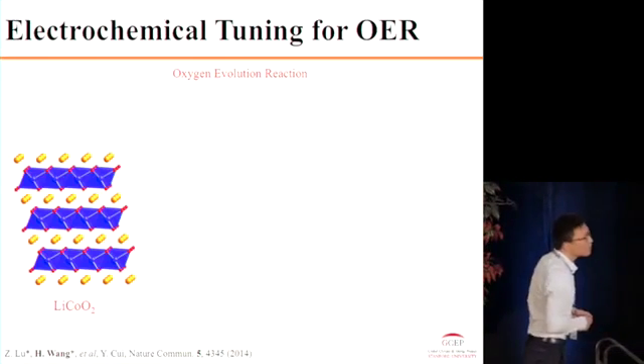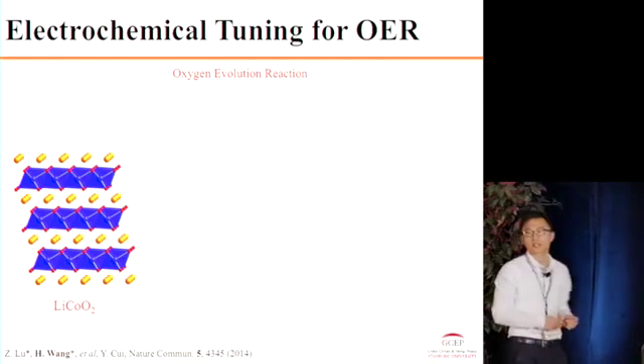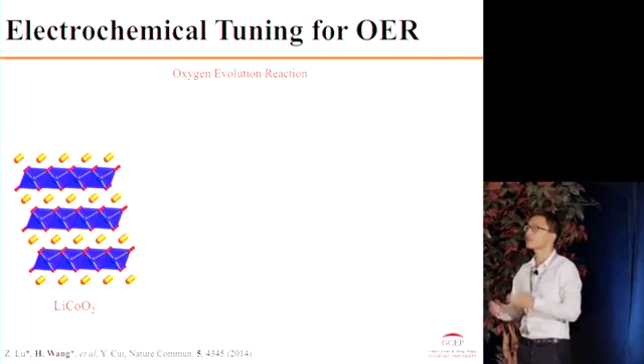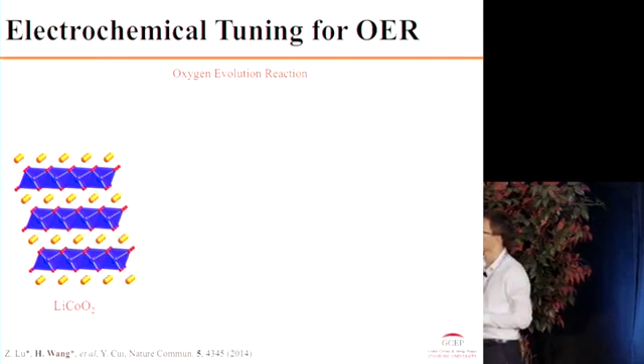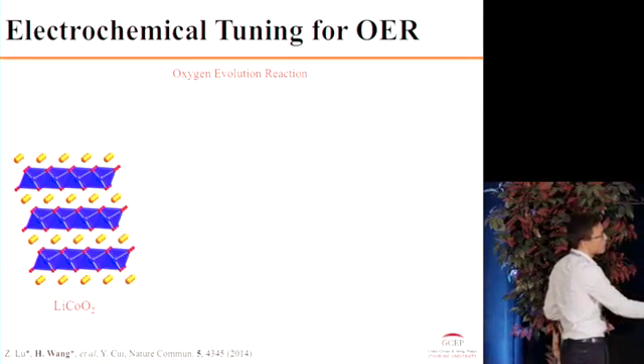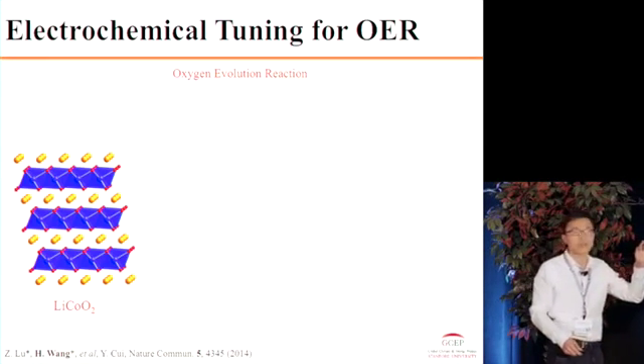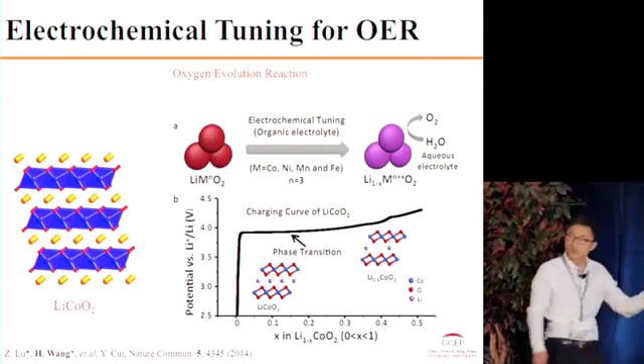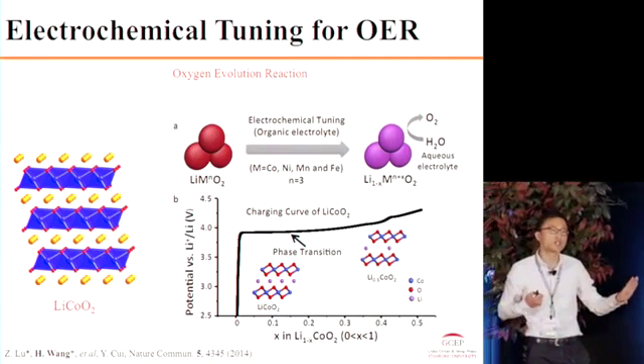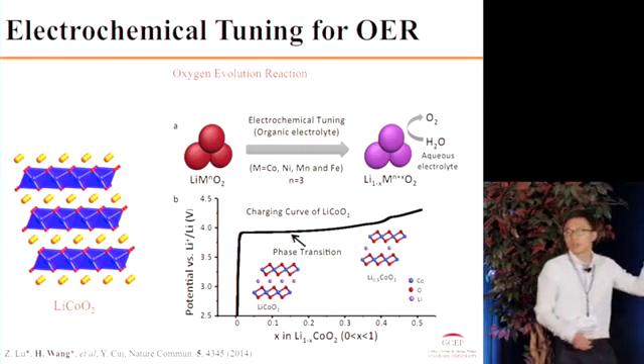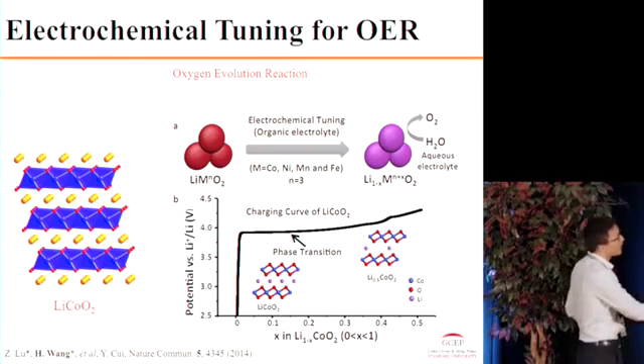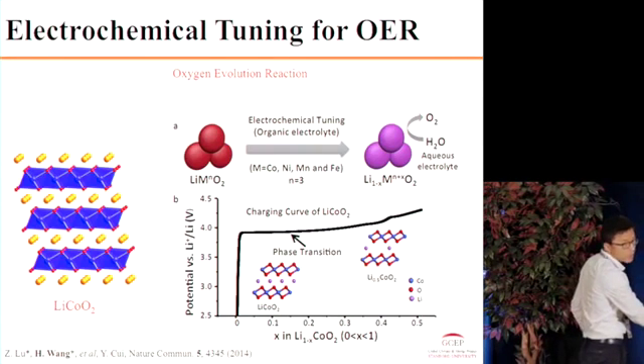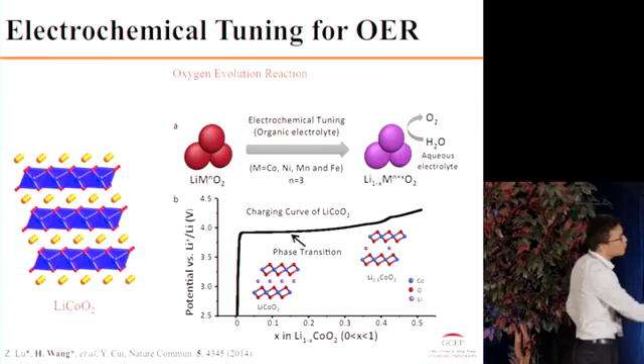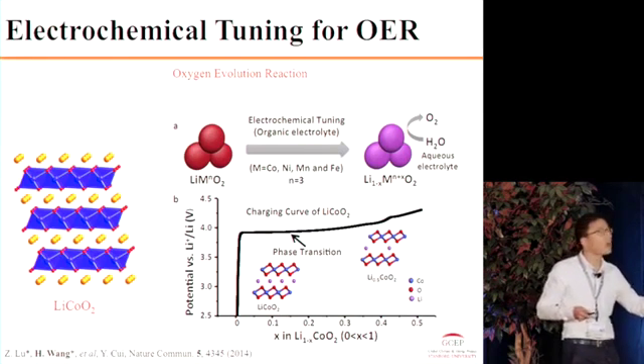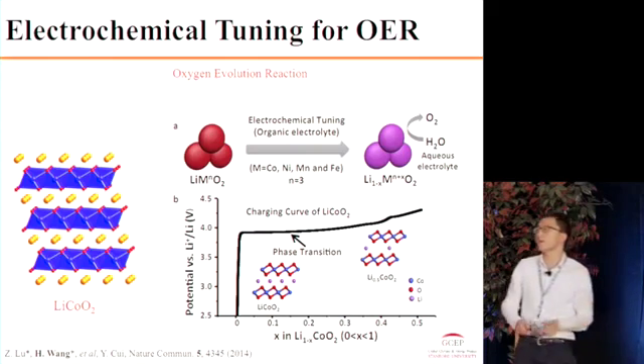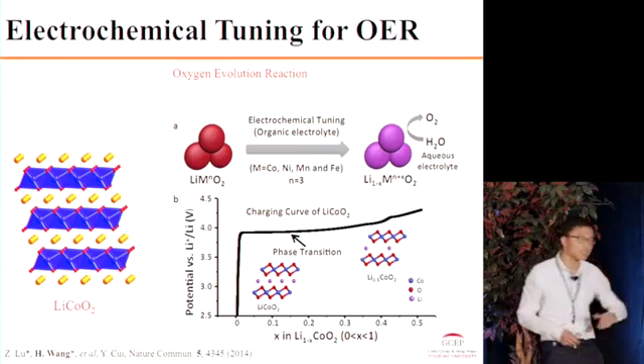So the first example we want to demo is lithium cobalt oxide, which is the traditional cathode, the positive electrode material in lithium-ion batteries. It is also a layered structure with lithium ions sandwiched by cobalt-oxygen atom slabs. And the way we want to do that is to extract some lithium and bring up the oxidation state of cobalt. As we can see, the average oxidation state of cobalt here is +3. And if you extract 0.5, half of the lithium, you can achieve a 3.5 oxidation state of cobalt, significantly elevating its oxidation state.